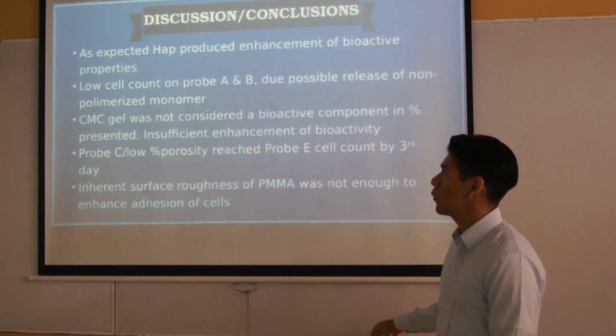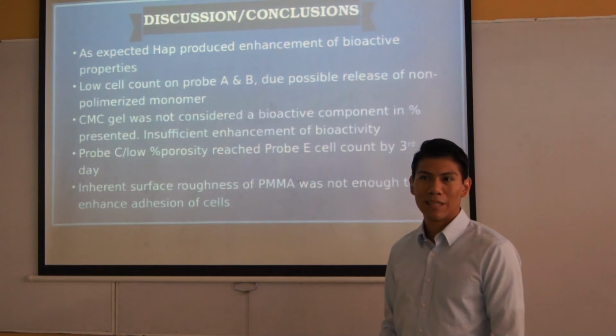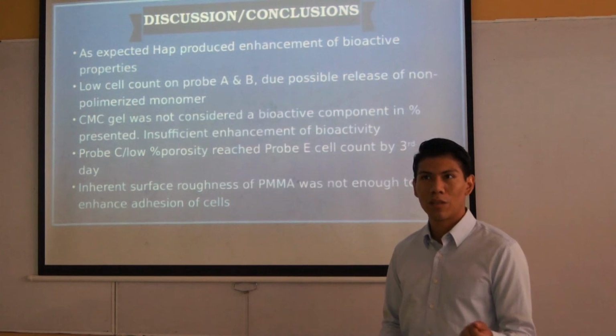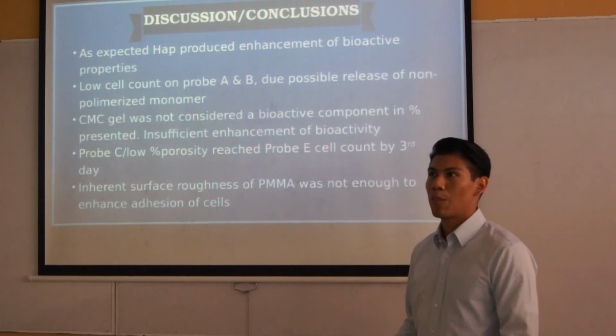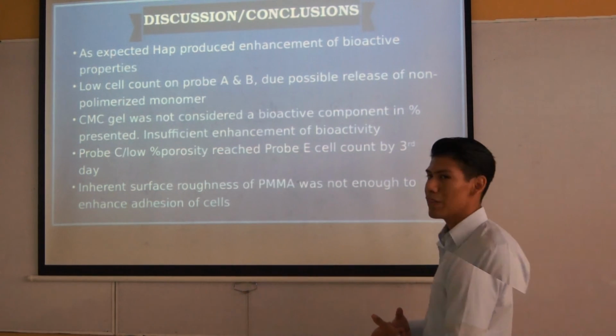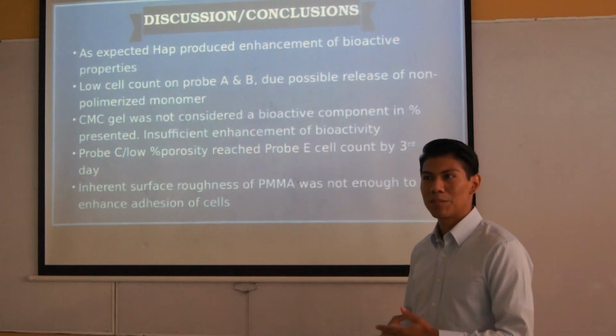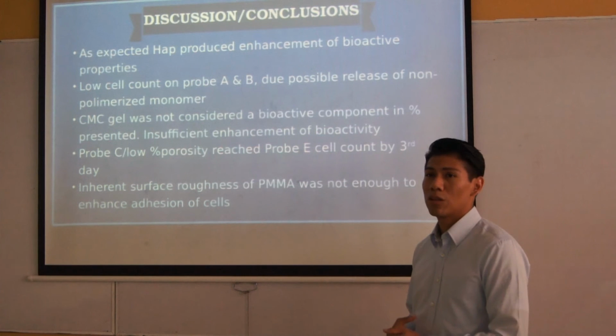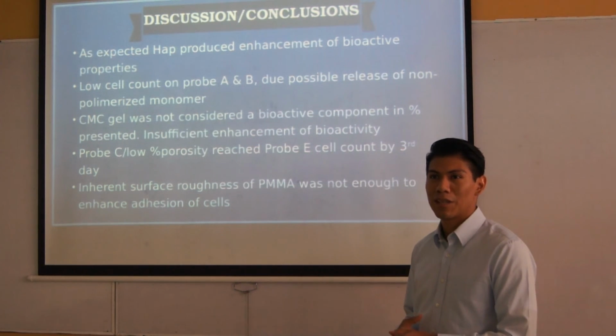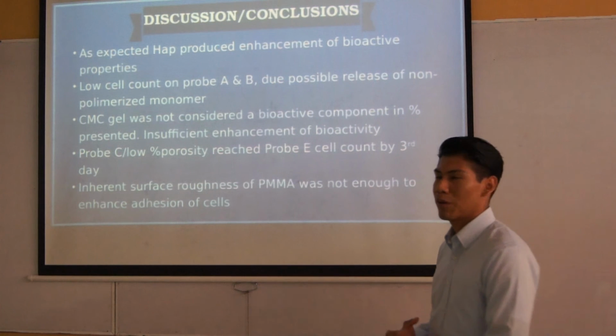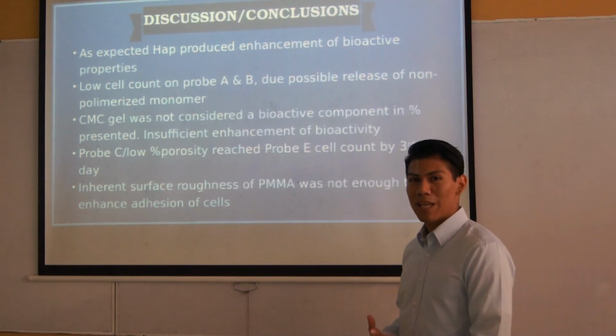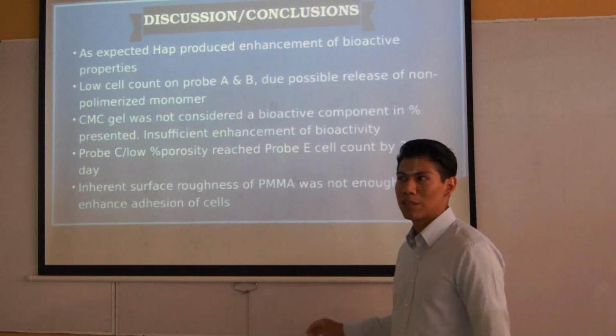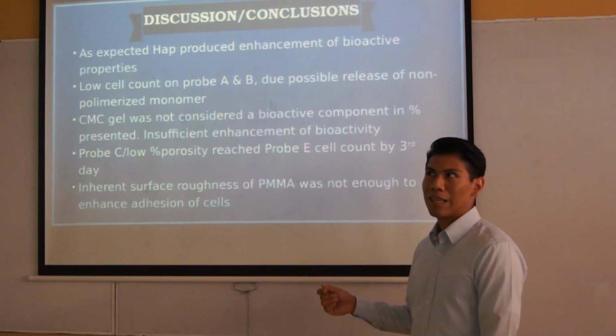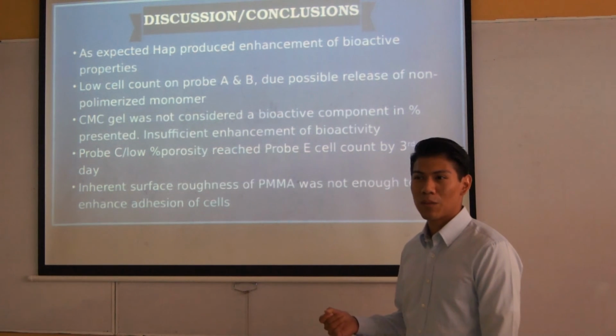The low cell count in probe A and B may be due to the high porosity in each of the probes. As we recall, it was 40% and 20% porosity, which may have caused non-polymerized monomer to be trapped in the matrix. This leads us to a conclusion that CMC in those high percentages may not act as a bioactive enhancer because it causes trapped non-polymerized monomer. If we compare probe C to probe A and B, which also had porosity, the porosity in probe C was so small that maybe the monomer trap wasn't enough to cause death or inhibition of cell growth.